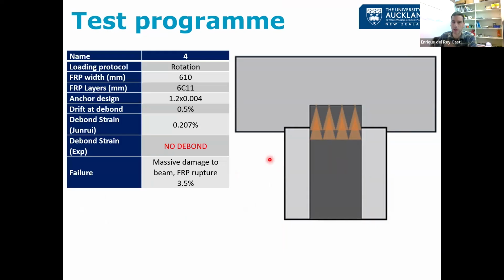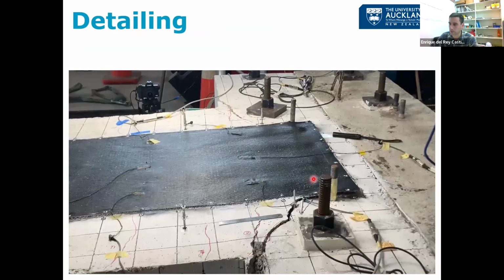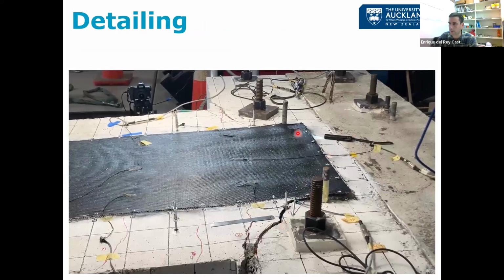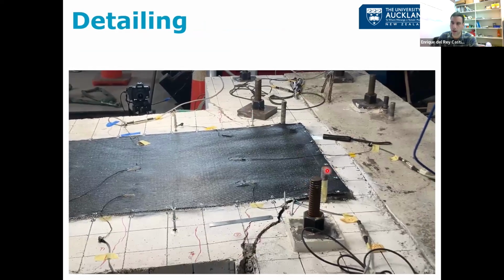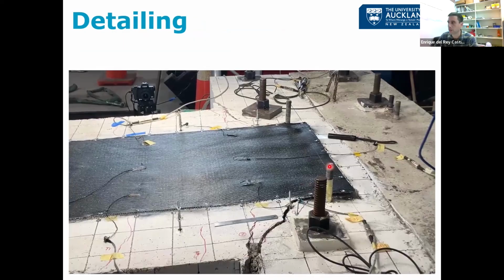Then we started to see issues when we went wide because we were breaking the beam. The anchors were not aligned in one line, so this row of anchors was taking the load before that one, and we damaged the beam. The FRP didn't debond, and this is what happened. We have a huge crack, and the whole beam is destroyed at 3.5% drift.